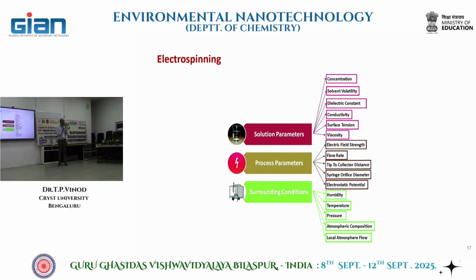Normally you cannot use water as a solvent, because water itself has a very high dielectric constant, which actually messes up the voltage you are applying through the DC. So it's not a suitable solvent. Also, water evaporates very slowly, so you will not get quick evaporation. You may need a heating condition also. So usually non-polar solvents and volatile solvents give you good results very easily.